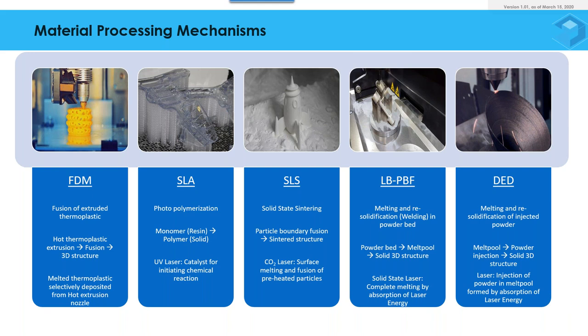The laser is a solid-state laser enabling complete melting of the powder — unlike selective laser sintering where only solid-state sintering takes place. Direct energy deposition is a process very similar to laser-based powder bed fusion, but the powder is not in a powder bed — instead it is injected through a nozzle. A melt pool is formed on the substrate into which the powder is injected to form a 3D structure. Both laser-based powder bed fusion and direct energy deposition can be related to welding processes we are familiar with.